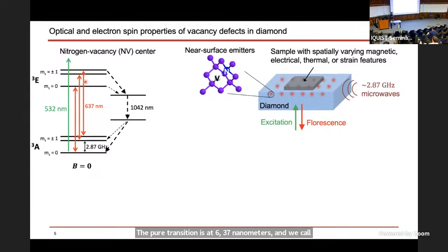And as the name suggests, phonon activity is a big consideration in this diamond crystal. The emission that you get, especially at room temperature, due to phonon relaxation, is fairly broad, going all the way from this pure optical transition at 637 nanometers to 800 nanometers. And the nice thing about this NV center is that you can polarize it optically. The way that happens is through these intermediate metastable states, which have different non-radiative decay rates from the spin states.